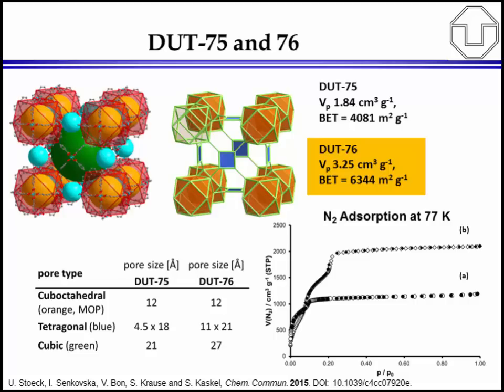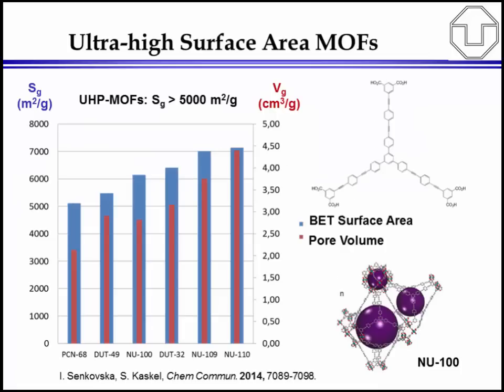And of course, these materials are crystalline, so all pores are very well defined, with well-defined accessible sites. So this was a recent example from my group. I have to say that our materials are not the record holders, but on the next slide we see the record-holding materials as published by some other groups from Northwestern University. The record is currently 7,000 square meters per gram, extremely high specific surface area.